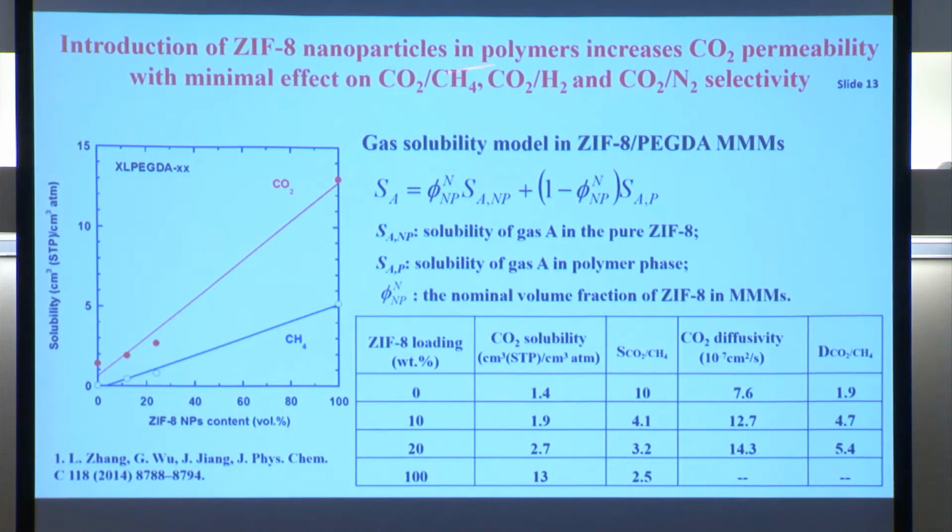So that means the introduction of ZIF-8 nanoparticles in the membrane increases the CO2 permeability dramatically, but has little effect on the selectivity of CO2 to methane, CO2 to hydrogen, and CO2 to nitrogen.